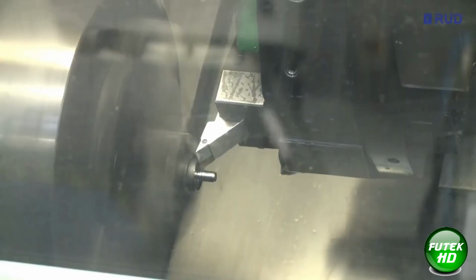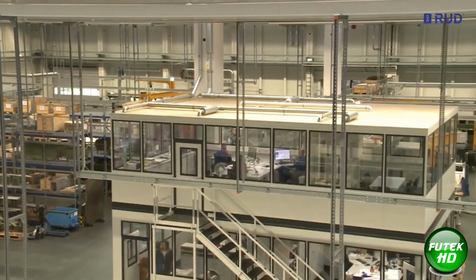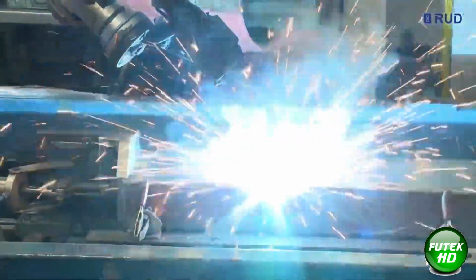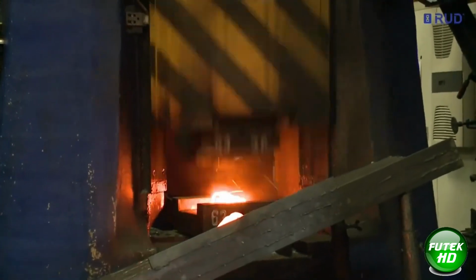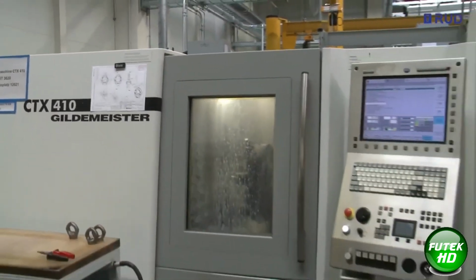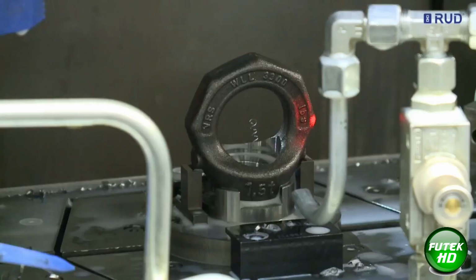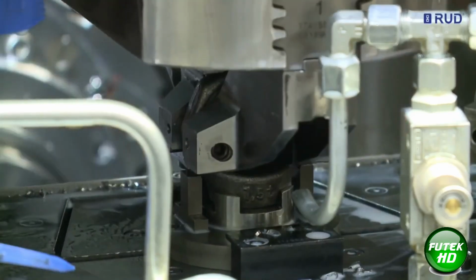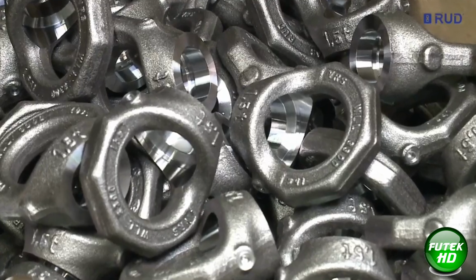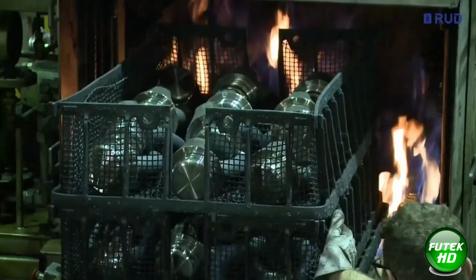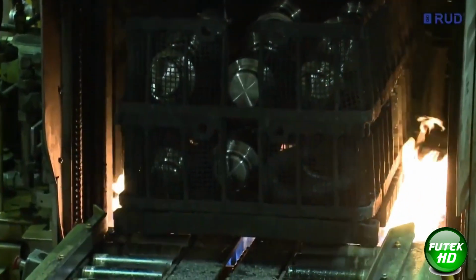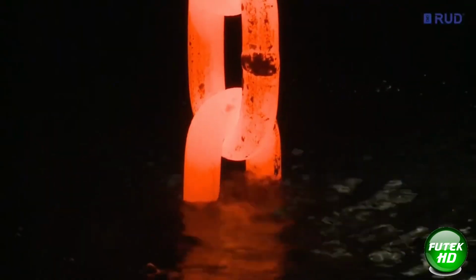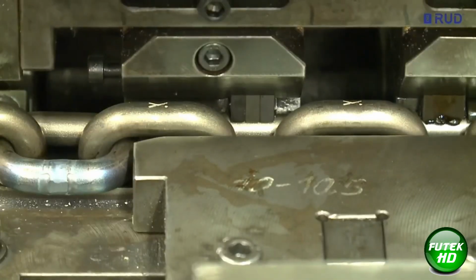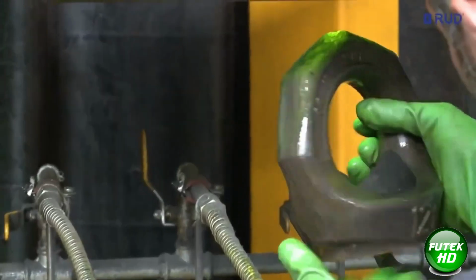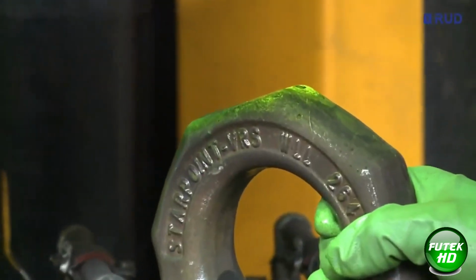Heat treatment is a critical process in chain production, ensuring durability under extreme conditions. Every safety-relevant component undergoes thorough crack testing before final processing and global distribution. RUD employs over 500 people at its Aalen site and around 1,700 specialists worldwide, relying on their expertise to maintain product excellence. A notable advancement by RUD is the development of the patented ICE material, which offers a 60% higher breaking strength than grade 8, while maintaining the same elongation and fatigue resistance.